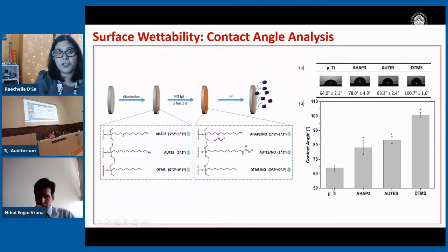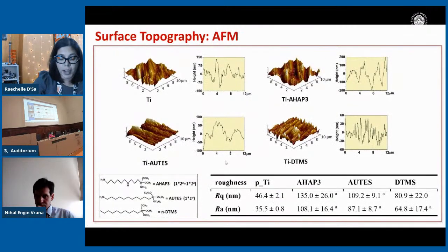So this is just the silanization reaction we have observed using contact angle. What you can see is that after we've immobilized the silanes onto the surfaces, we have an increase in the hydrophobicity of the surfaces, which is because of the alkyl groups of the silane molecule. We then looked at AFM analysis to see what happens in terms of the surface topography, and we find an increase in surface roughening from our titanium surfaces after we add the silane groups. This increase in roughening could be due to multiple layers of the silane that form on the surface, and also over here you can see, for example, the silane sometimes aggregates in clumps onto the surface.